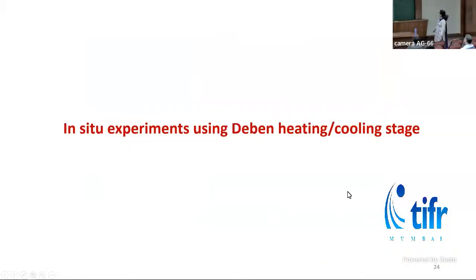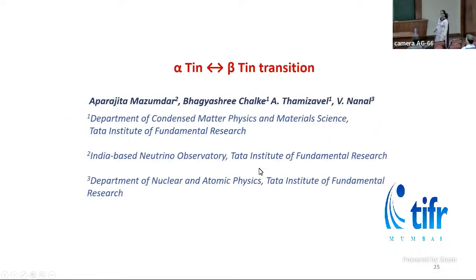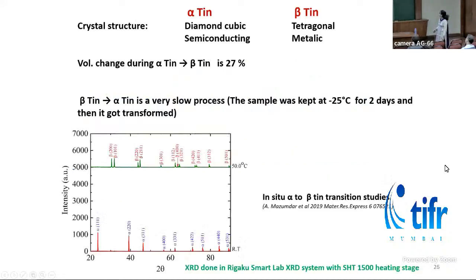Here are some in situ experiments done using the heating and cooling stage in SEM. We have studied alpha tin to beta tin and beta tin to alpha tin transition in SEM. Tin-based alloys will be used as detectors in the India-based Neutrino Observatory. So that's why this work is important.